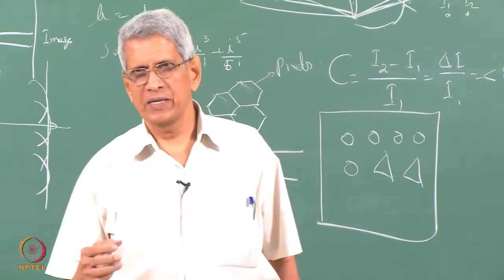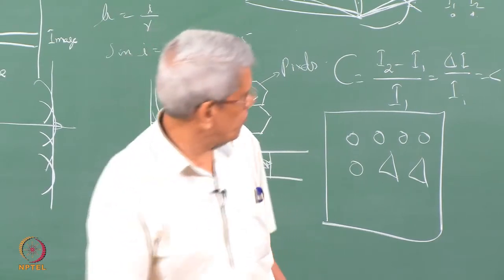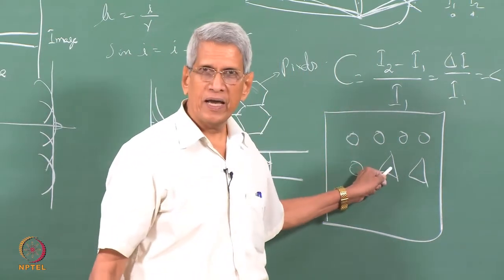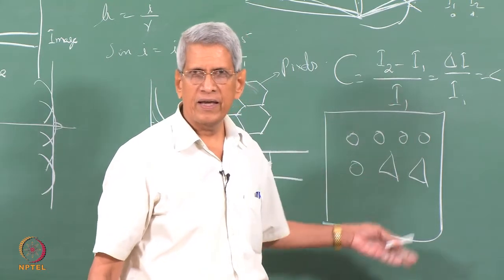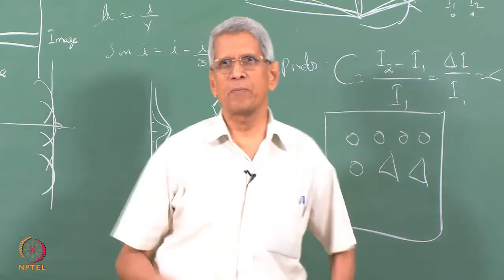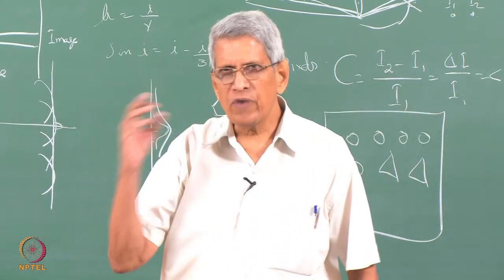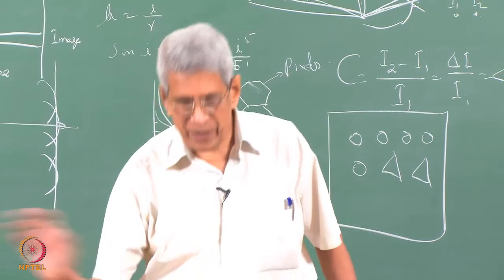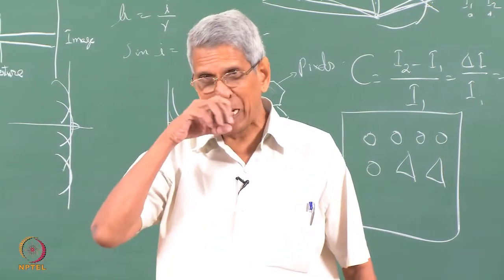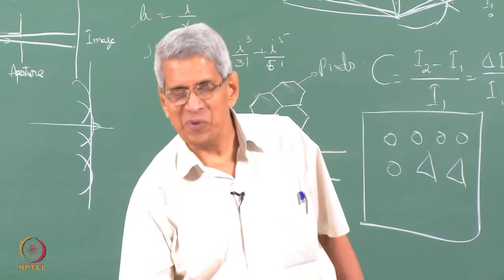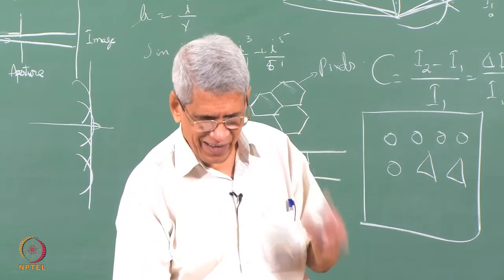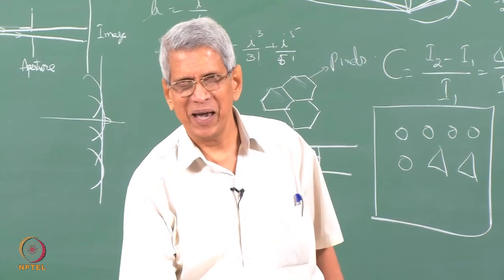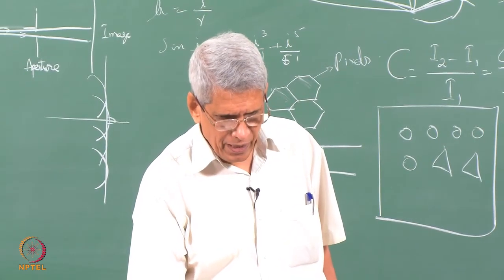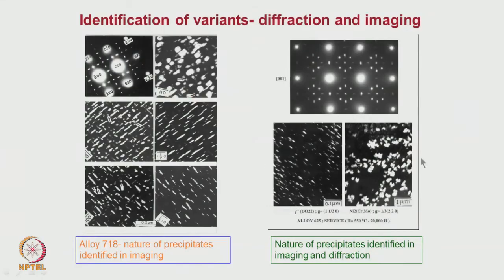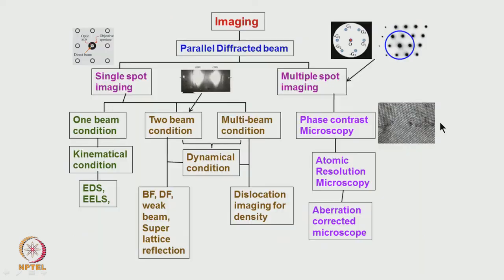Suppose I put a dark field image from some specific reflection. If both of them belong to the same precipitate and they have the same orientation, only the way they have been cut it appears, then all of them will appear bright. So there are ways in which it has to be done. That part of it is what is being covered in the practical electron microscopy, and that is not what I am doing in this class, because here I am talking essentially about the principles of electron microscopy and how the image formation happens. But in a brief nutshell, this is the way we form the bright field and dark field images.